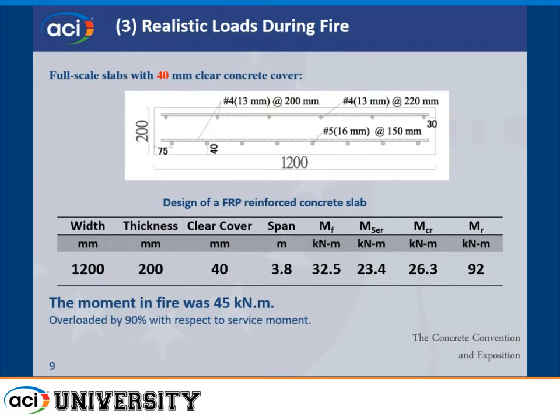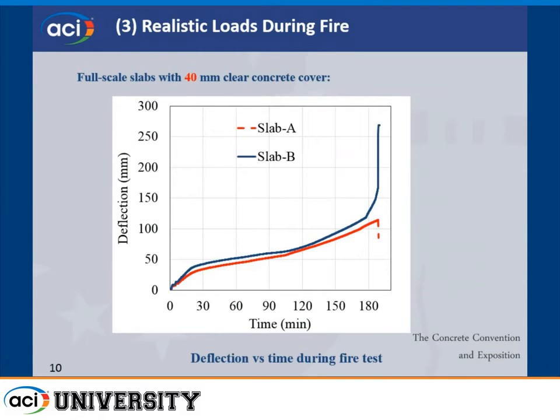So then we tried it with 40 millimeters clear cover, so that's basically about an inch and a half. We actually got a little more strength in this design. We applied the same moment in fire, and deflections were a little bit lower in this case. But once again, we actually got 3 hours of fire endurance, even in this scenario. I didn't think we'd even get the 2 hours in this case.